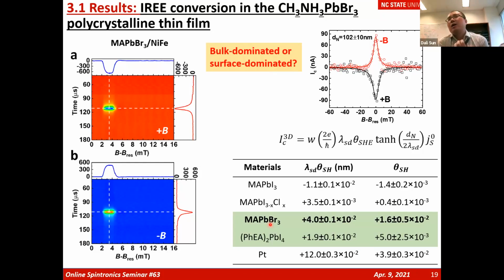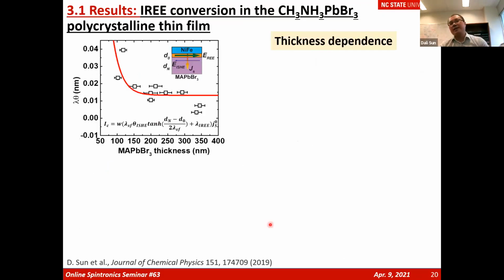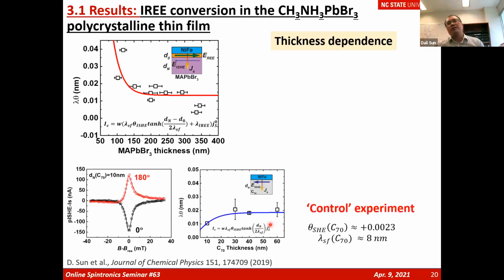Is it due to the bulk effect or a surface dominated effect, which can be attributed to the Rashba effect? So we do the thickness dependence to further study the spin-to-charge conversion efficiency as a function of thickness up to 300 nanometers. Surprisingly, we see the spin-to-charge conversion efficiency decay and then saturate at high thickness. This is not the ordinary behavior, and it does not fit the spin pumping model. If we choose a typical material like C70, which is like a fullerene, the spin Hall angle or spin-to-charge conversion efficiency should increase and saturate at a higher thickness, following the tanh(d/2λ) expression here. What we observe is decay first and then saturation.